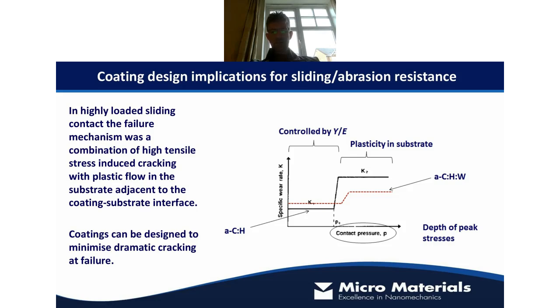What I've shown so far essentially is that this picture of understanding wear rate and contact pressure, actually if we consider the depth of the peak stresses, then we have some better understanding. What we can say is if the peak stresses are well within the coatings, then relative abrasion resistance is controlled by this factor of Y over E. But at higher load, plasticity in the substrate becomes important.